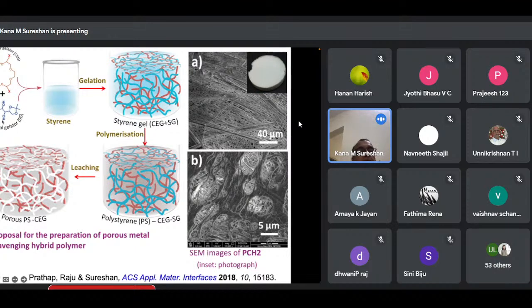And this is another gelator, which I have already shown for the oil spill recovery. So we have taken two gelators and made a gel out of this before polymerization. And now I have shown this is forming one kind of fiber because they are self-assembling. The other crown ether is forming another kind of fiber in the matrix. Now you polymerize this one by putting a radical initiator and you have a really thick block of this polymer material. Once this is polymerized, you can wash off this particular one, the blue one actually.